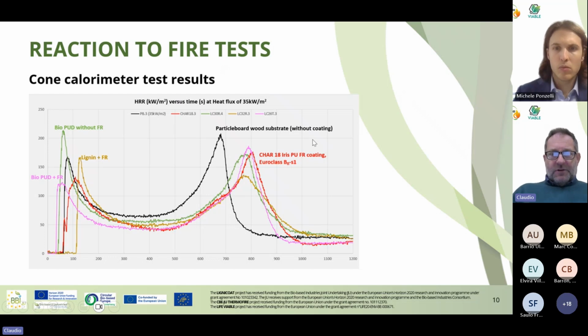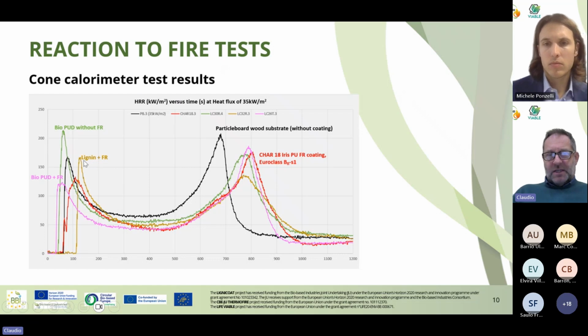This is a typical result. I don't have shown another before, so I will only say that with these results, you can see, for example, this sample is lignin-based. Its combustion starts later, so it's better than the other specimens in that respect. The heat release is also smaller than this one, for example. You normally observe a behavior like this. You have a flash at the beginning, then the combustion goes slower, then you have a stronger combustion later on. And all in all the area under this curve is the total heat release. The smaller it is, the better the result will be. This chart is our benchmark. All in all, you see that this lignin-based material is kind of doing better, even better than a product that is now a market reference.